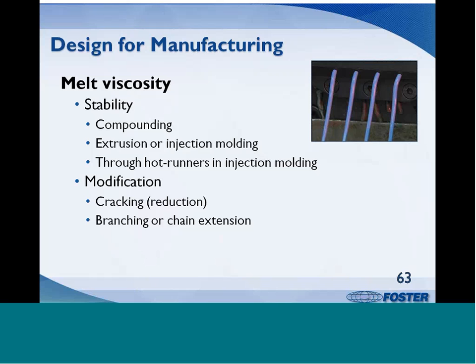To get the right viscosity, some polymers, such as polypropylene, are cracked or sheared at high temperatures in the presence of a free radical source. Linear materials, such as polyesters, can have their melt viscosity and melt strength enhanced by reacting them with a chain extender.